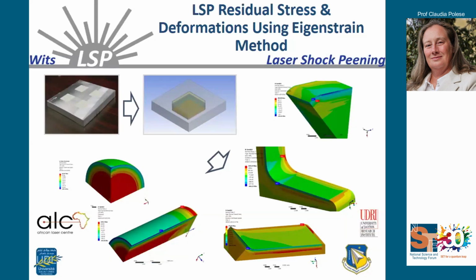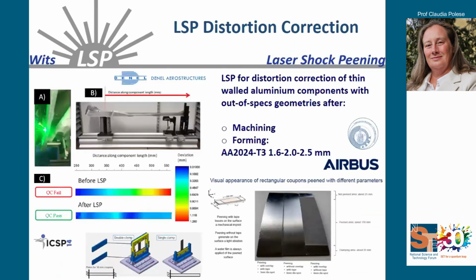So in this case, we're doing finite element modeling together with colleagues through the African Laser Centre. That means we can use the data and information coming from very simple samples that we can process, and try to apply that to real components with much more complex geometry. In this case, we can not only increase the life, but also do interesting things like correcting distortion coming from previous processes, for example machining or forming.